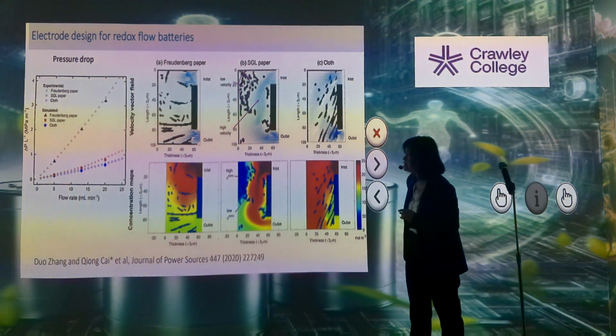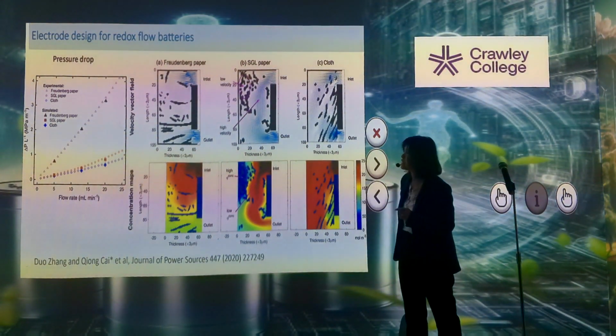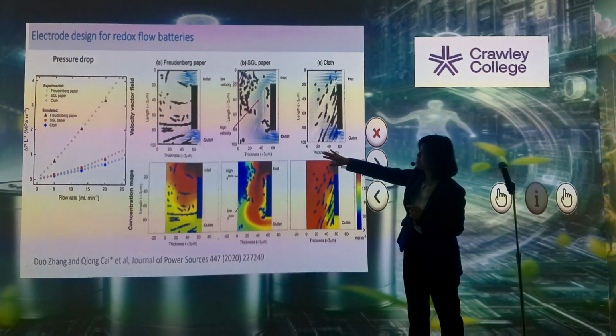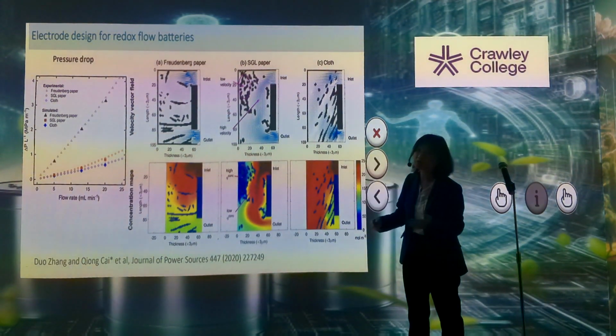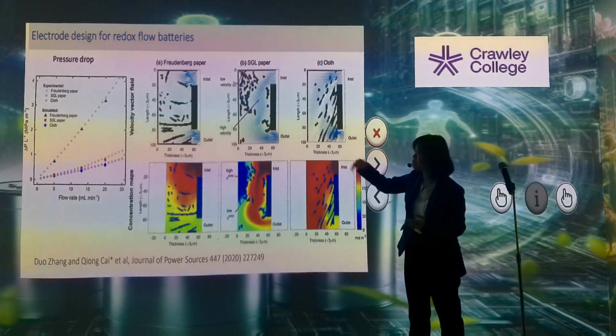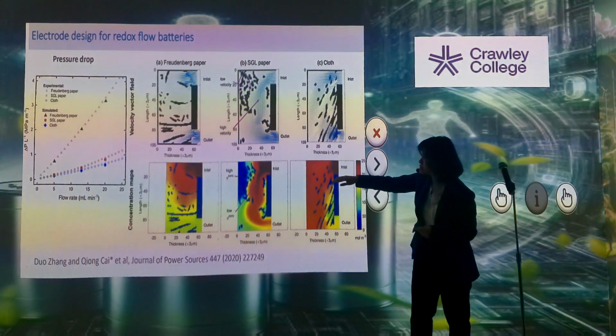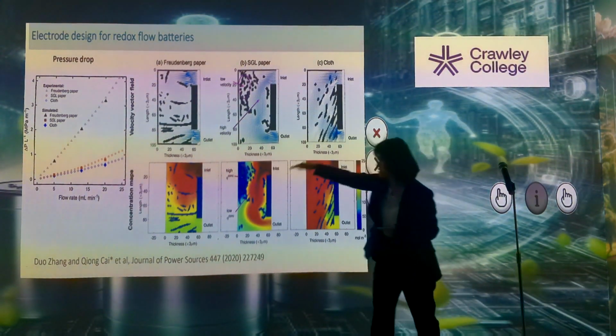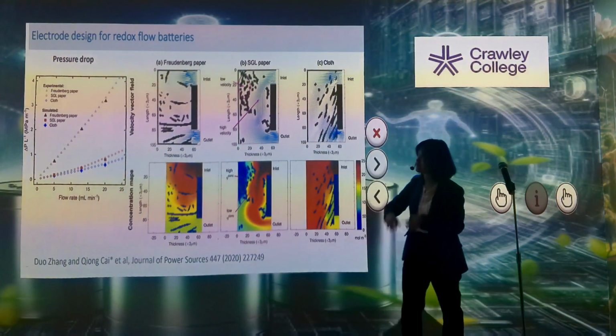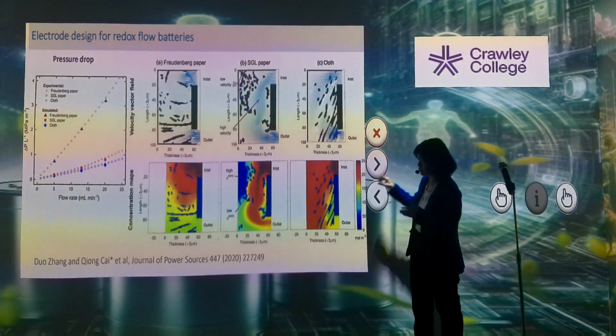So I'm in chemical engineering department, and the pressure drop is a critical matter here. If you have a low pressure drop, meaning that you will have lower energy consumption to run this battery. So we want lower energy, lower pressure drop. And you can see that both the SGL paper and the carbon cloth has a lower pressure drop because they have bigger pores.